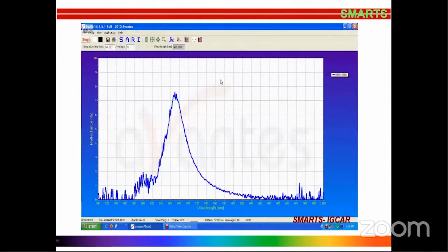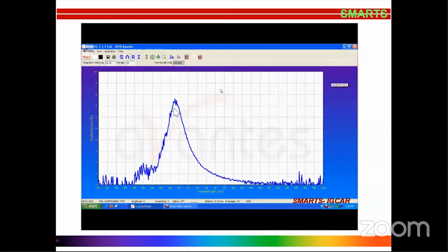Now the problem that you face in colloidal systems is the interparticle spacing. Again, you have a solution with magnetically polarizable emulsion. In this video you see a Bragg peak. This is the Bragg peak you see in crystals with X-rays. X-ray scattering is used because the interparticle spacing or the lattice spacing falls in angstroms, so you have to use X-rays to get the diffraction pattern or the scattering. In this case, the droplet size is of the order of 200 nanometers, so you have a length scale which is comparable to the visible wavelength. So when you apply a very strong magnetic field, you see a Bragg peak at lower wavelength.